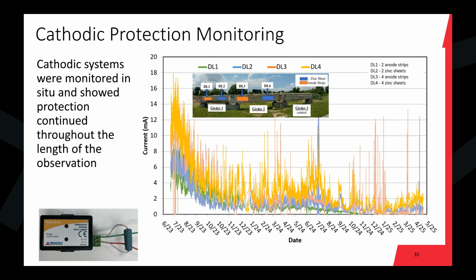This is comparable to what we've been looking at as our starting point if we hadn't had a sectioned girder. And the real takeaway here is you do see fluctuations, and these are based on the times of year. We're going to see the protection current is lower during the winter because the ions move through the concrete slower. So there's going to be less active corrosion at that time, even though we're applying more salt. And then during the summers, when things heat up, things move a little bit faster. So around May, June, July of 2024, you're seeing the current increase. Then it decreases again for the next winter.